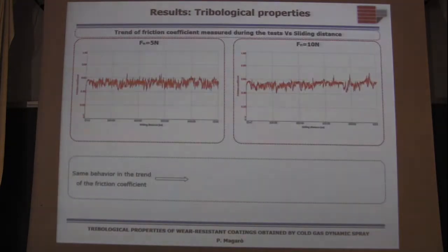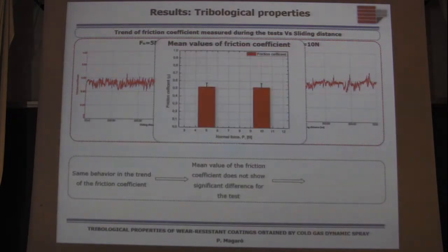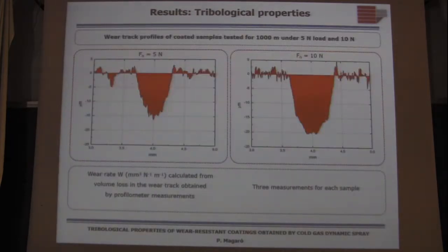So we can observe more or less the same behavior in the trend of the friction coefficient. In fact, the mean value of the friction coefficient does not show significant difference for each test. And this suggests that probably oxidation phenomena do not occur during the test.